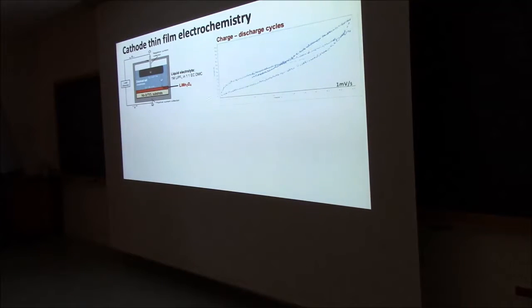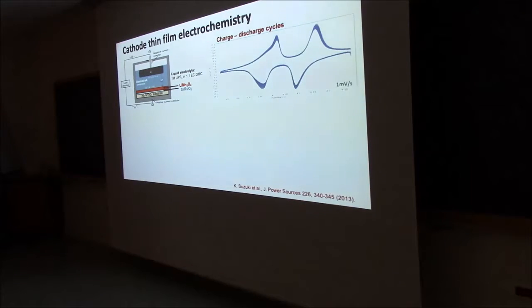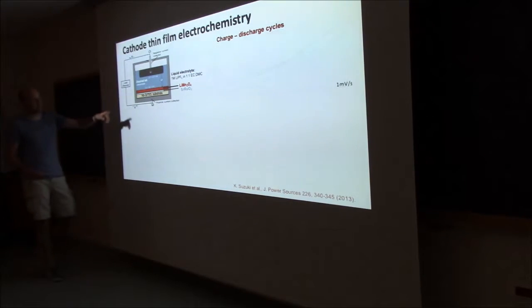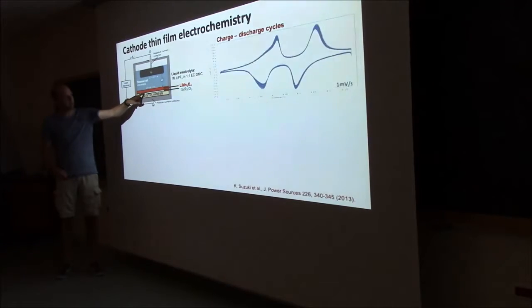So I would say this didn't work. Something similar like ferroelectrics go banana. So it didn't work. And then it's like, okay, we didn't grow the material well, maybe the lithium level is not good enough, but there could be other issues. And there was something already explained in literature, that what you needed to do is to put here the thin film of strontium ruthenate in between.